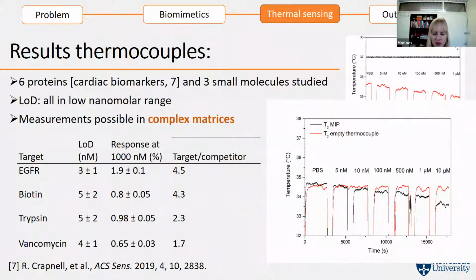And we've done this for a range of different molecules. So we were able to detect all of them in a very low concentration range, all in the nanomolar range, which is enough for trace detection. If you had a thermocouple not functionalized with anything at all, you would see no difference.